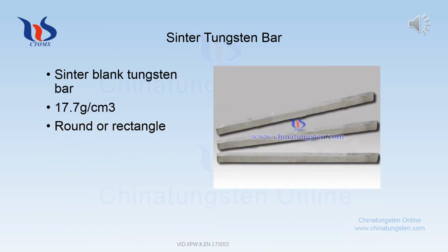Sintered tungsten bar is made by sintering the pressed bar in a sinter furnace. After sintering, the density of the bar will be about 17.7 grams per cubic centimeter.